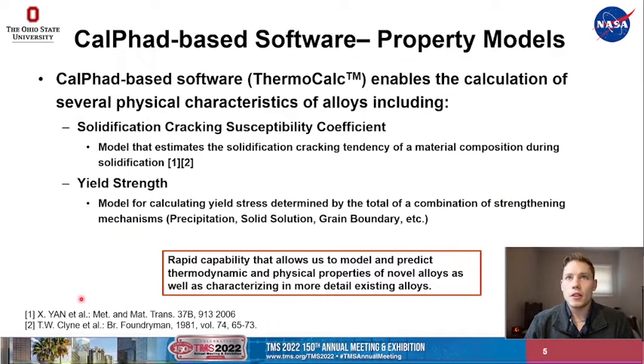So CALPHAD-based software has undergone a lot of development over the past several years, and one development was within the property model that Thermo-Calc uses in order to calculate different material properties. Recent updates have enabled the calculation of several physical characteristics of alloys, including solidification cracking susceptibility coefficient, which is a model that estimates the solidification cracking tendency of a material composition during solidification, as well as a yield strength